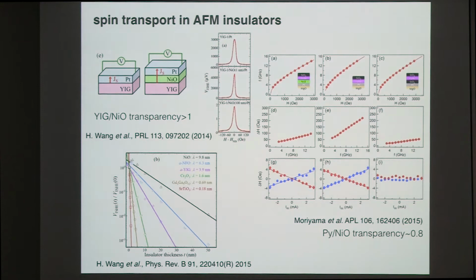And Ohio State also ran a lot of other tests of all the materials. We can see that not every material is very good for spin current transmission. Some materials are pretty short. But all of these works show that you can pass spin in antiferromagnet insulators. So this opens the possibility to further explore this insulating antiferromagnet direction.